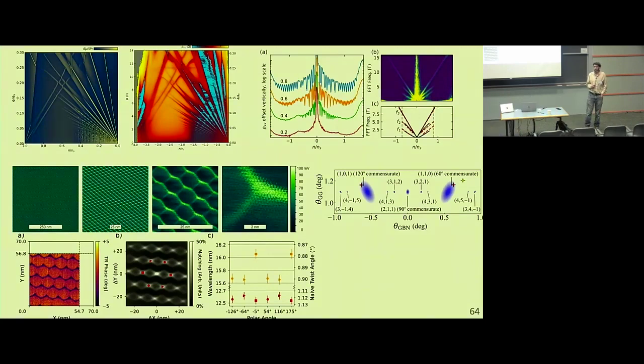So when you quantified the disorder, you mentioned some pretty high mobility number, but I wonder if the mobility is the right way to quantify disorder in this context. I'm asking because, for example, in gallium arsenide, we know that a sample with higher mobility may actually have a much poorer energy gap. And so what about this situation? Maybe you have a longer range disorder where mobility is not the right way to quantify.